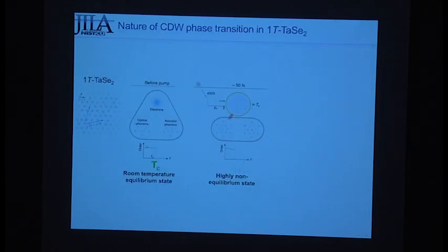And so in new work, we looked at this tantalum diselenide material, where the electrons are in an insulating state, and after you excite with a femtosecond laser, the charge gets redistributed spatially. Think about that. That's a very big change in charge distribution, and you're going to excite phonons when you do this.